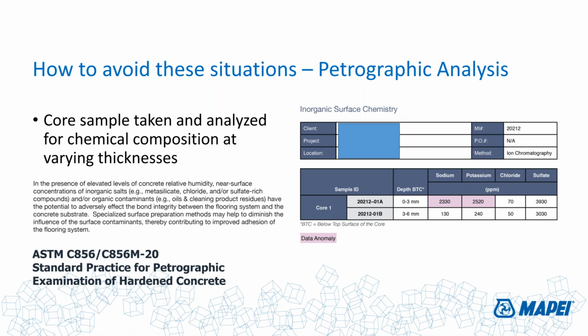Unfortunately, we oftentimes go to core samples when we're trying to analyze a problem. What happened? Why did this floor blow up? My calcium chloride numbers were good. My RH numbers were good. My pH numbers were okay. Everything looked fine. Why did it still blow? This is 9 times out of 10 the reason why that happens.